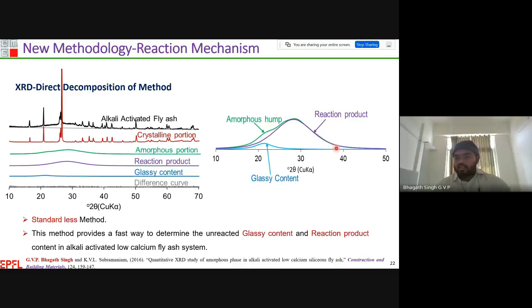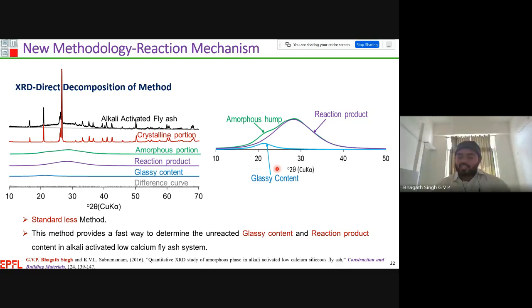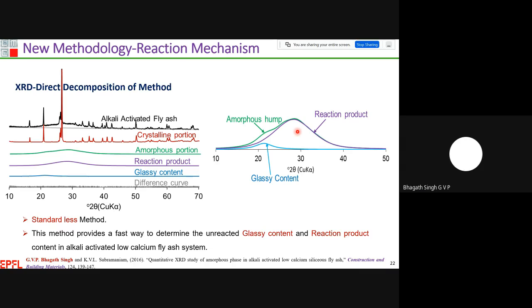And by using the nonlinear fit algorithm, I have deconvoluted this portion to see how many phases are present in this region. Here I am able to fit two phases, one at a lower theta angle, another at a higher theta angle. The lower theta angle represents the glassy content present in the alkali activated fly ash, the glass which is not reacted. And the higher theta angle represents the reaction product formed during the activation process at the particular time.